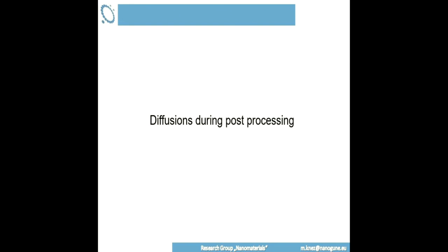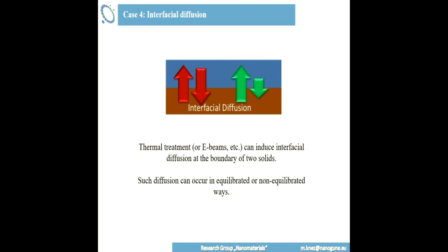I just wanted to mention a few processes which we observed in the literature and in our own labs. You need to be aware of them in case that you need to heat treat your sample after the process. The first case, so this is case 4 in the sequence here, is that if you have two solids, so we're not talking about polymers anymore, at the interface of two solids, you will also have diffusion processes, if you heat high enough. And this interfacial diffusion can be induced thermally or with E-beams or whatever, and it can be equilibrated or not. What do I mean by that?